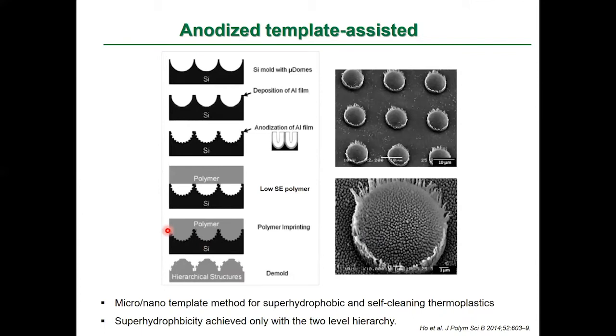So the anodized templates are well known. We can use the templates for fabricating superhydrophobic polymer surfaces. For example, you can see the silicon molds with the micro domes, where they deposited aluminum and further anodized, and the polymer is imprinted, and the template is removed, and so the already hydrophobic surface simply becomes superhydrophobic.